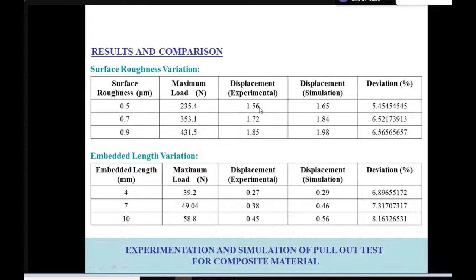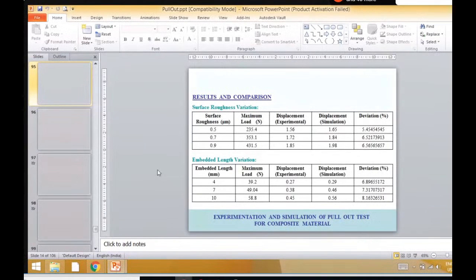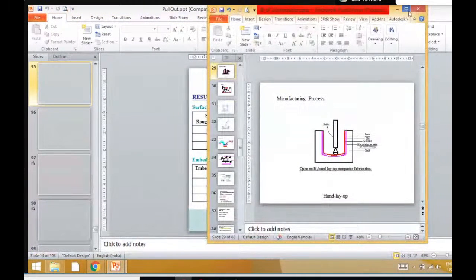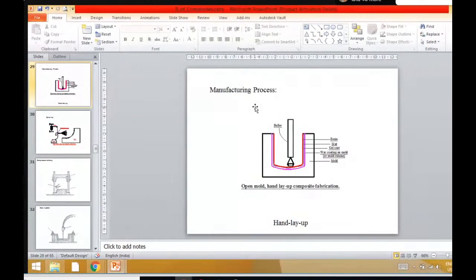All these results we find: in the case of surface roughness the deviation is 5 to 6.7, and similarly for embedded length also, when we take the different embedded lengths 4, 7, 10, the deviation is in the range of 7 to 8.16. So this is how you can simulate the pull out test for any composite material and any design which you need to take up for designing the composites. Now I'm coming back to my original slide where I started with the composite.